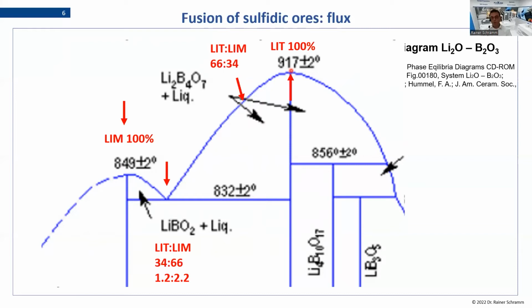And so one big difference is the melting point, but the other big difference we have to take into account is the glass forming. Boron oxide, which is way down here, really forms a good glass. This is also the case for lithium tetraborate, but then it's decreasing until lithium metaborate does not give a glass. The crystallization speed is really too quick, so that we are not able to get a glass out of it. And this is now a bit our challenge: going in that direction, which means increasing the metaborate part, the ability to form a glass is decreasing continuously. So that's why it's sometimes difficult to use such a flux to get immediately a glass. So you need a lot of optimization of your recipe until it works.